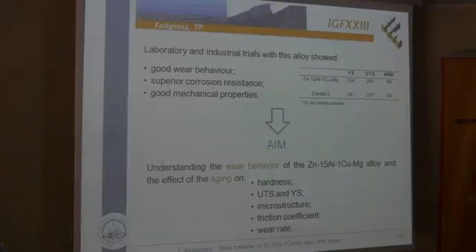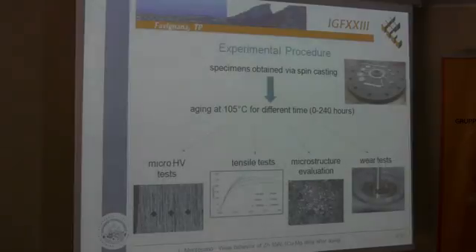So the aim of the work I'm presenting is to understand the wear behavior of this alloy, and in particular to study the effect that aging has on, first of all, the wear behavior, and also on the other properties of the alloy. To hit this goal, we started with the production of samples via spin casting. So we produced all the samples for the tests we did later.